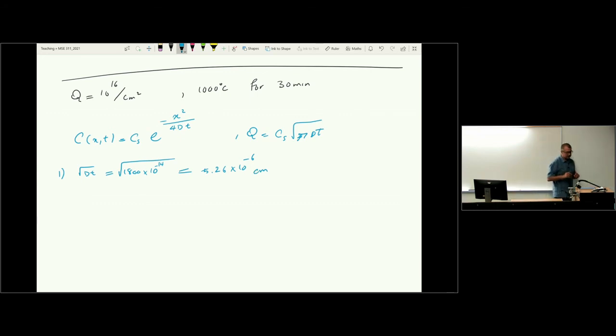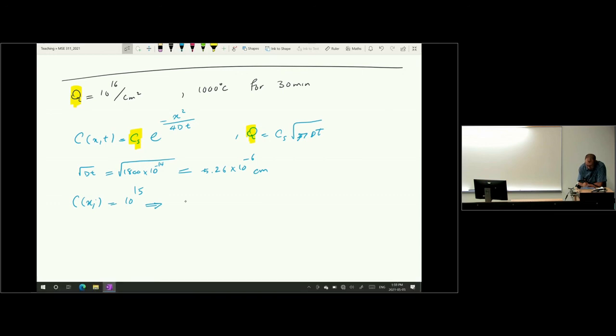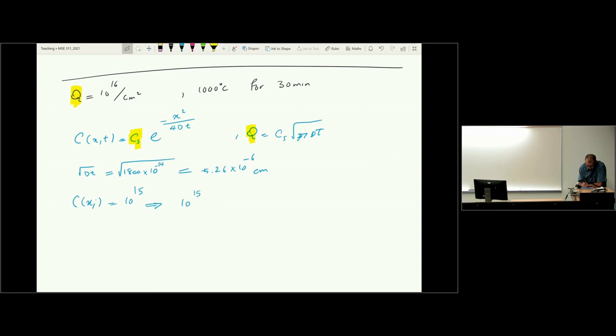Once you know that, you can solve to find the junction depth. So the second step is to see where C of x at x_j is equal to 10 to the 15. So I put it in the equation I have over there. In this case, notice that I don't know Cs, but I know the areal density, right? The constant dopant concentration of 10 to the 16. So I know Q. So I plug that in here. Q, 10 to the 15 for the junction depth is equal to, for Cs I put Q over square root pi Dt, so Q over square root pi Dt e to the minus x_j squared over 4Dt. And because I know Dt and I know Q, I can solve it.